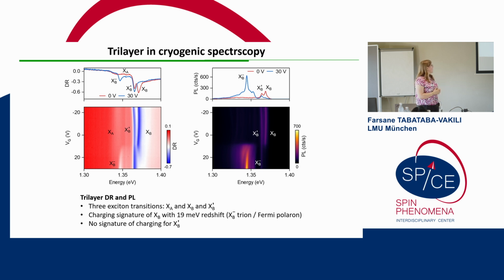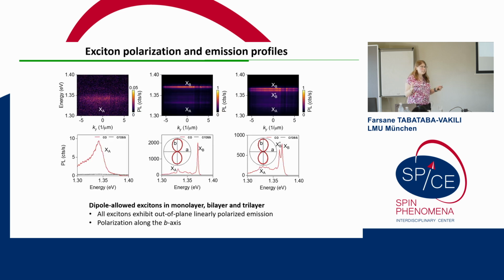All right. So all of these excitons have an in-plane polarized optical dipole with out-of-plane emission, which we can see here in these k-space dispersions. So we have highest intensity at small in-plane k vectors, and they're all highly linearly polarized, which we can see here in these polarization-resolved measurements. So basically, the entire emission goes along the b-axis and no emission along a. This is also because of this quasi-one-dimensional character, because of this anisotropic band structure.